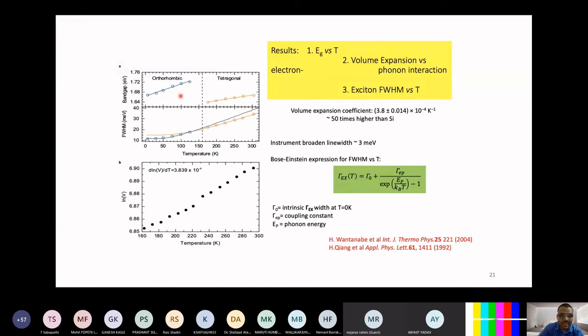And in order to explain this positive temperature coefficient data, we did an experiment where we do temperature dependent XRD. And the temperature dependent XRD allows us to determine the lattice expansion coefficient. And we realized the lattice expansion coefficient of this perovskite semiconductor is 50 times higher than silicon. And that suggests why we do see a positive temperature coefficient for the halide perovskite, in contradiction to what we know from our textbook knowledge of gallium arsenide and silicon.